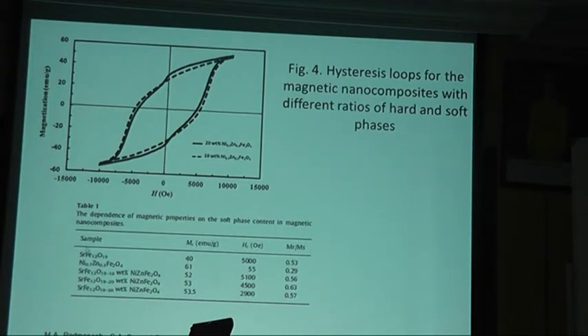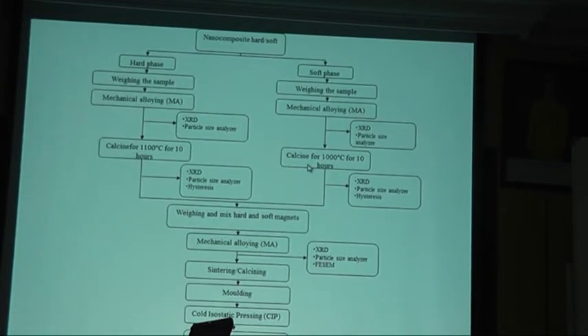10%, 20%, and 30%. So for 20% of nickel zinc, they get 0.63 remnant ratio, which is considered very high for an experiment. We can see the straight black line here is for 20% nickel zinc and 80% strontium ferrites. We can see they enhance the remnants, but that's normal in any magnets. If we up the remnants, we have to accept that there's a drop in coercivity. Okay, this is, I would say, the proposal for making a hard-soft nanocomposite.